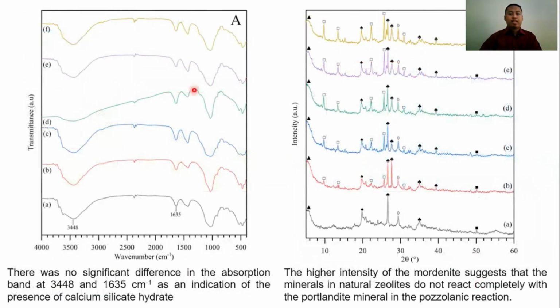Based on the infrared spectra of all variants of the composite, there were no significant differences in the absorption bands at 3,400 and 1,600 as an indication of the presence of calcium silicate hydrate. Meanwhile, in the diffraction pattern in figure B, the higher intensity of the mordenite suggests the mineral in natural zeolites does not react completely with the calcium hydroxide in the pozzolanic reaction.